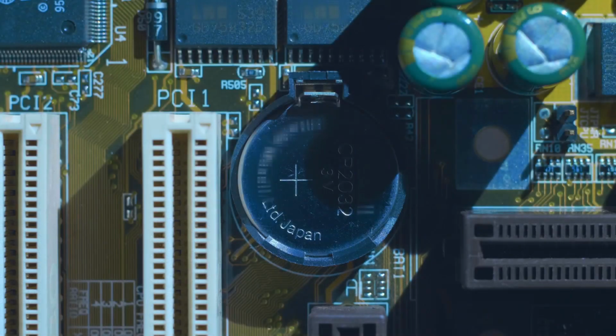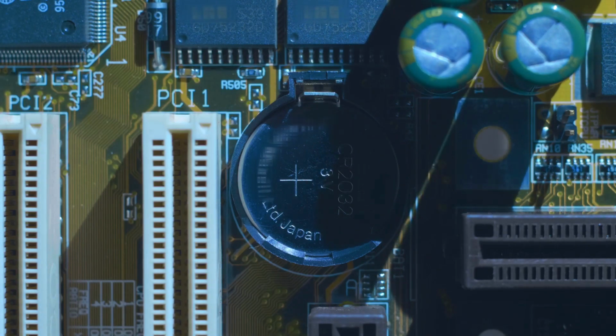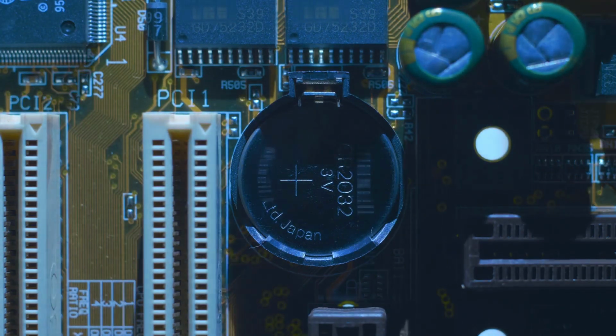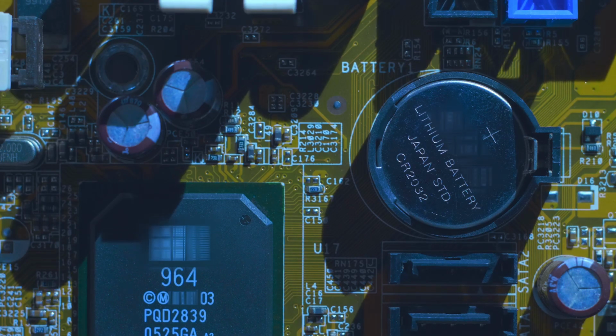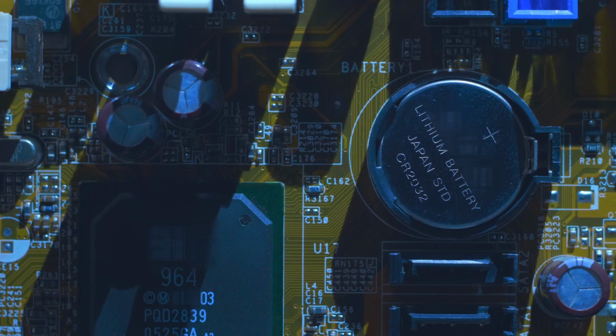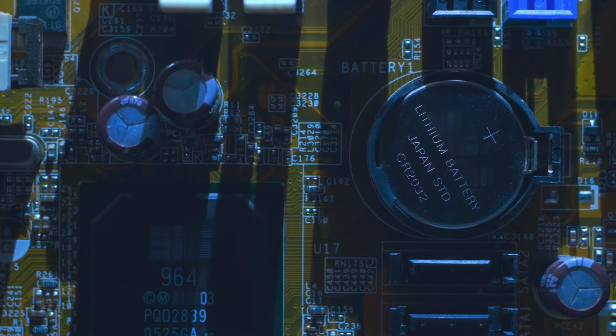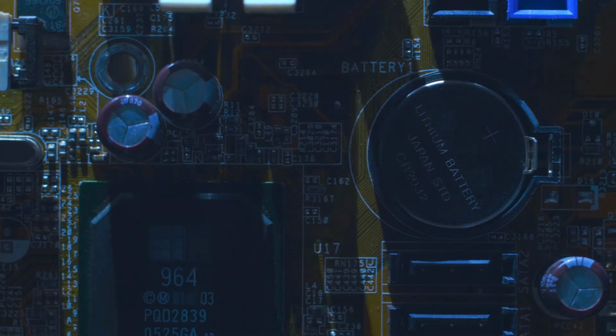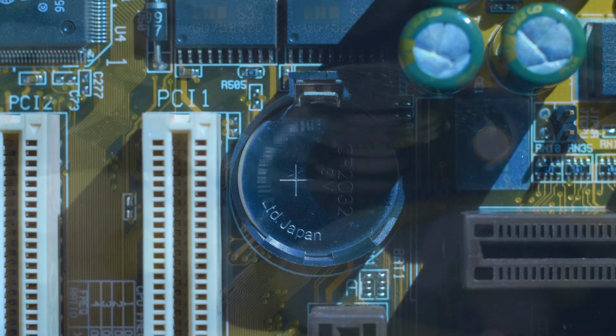But what's crazy is that even after all this, these batteries should never have worked. See, when you charge the battery for the first time, lithium ions move from the cathode to the graphite anode, and here they react with the electrolyte to form this weird, complex patchwork of compounds that build up on the anode surface. These parasitic side reactions could keep going on indefinitely, using up all the lithium and destroying the cell.